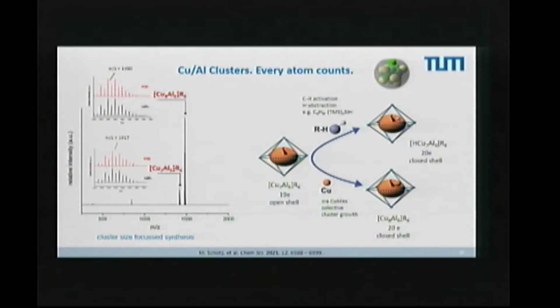So if we treat this kind of mixture with, for example, a hydrocarbon, in this case it's a silane, or with additional copper. So we make these compounds here, we crystallize it, we have single crystals, we know exactly the composition. Two experiments. One is treating the solution with this silane, which is a hydrogen donator, or treating the solution with our copper precursor, which is just donating copper atoms. Now, since the copper 7 needs 1 electron to be happy, it just takes 1 copper atom, not 2, not 3, just 1. And this is exactly what happens. And since it needs 1 electron, the cluster doesn't care whether the electron comes from the copper or from the hydrogen atom. So the thing is happy with taking the hydrogen atom as well.